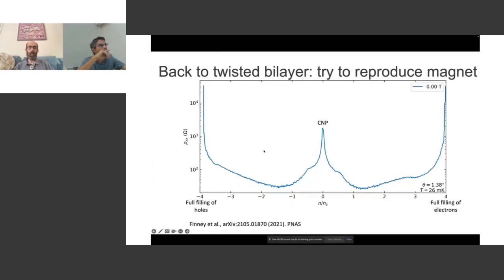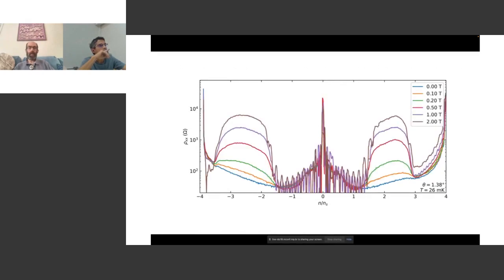But this changes if we turn on a magnetic field. And so as we increase the magnetic field, these sweeps look very different. You can see that there's a rising resistance in this broad range of densities of electrons. And this can be as much as 300 times. This is a log scale on the resistance axis.